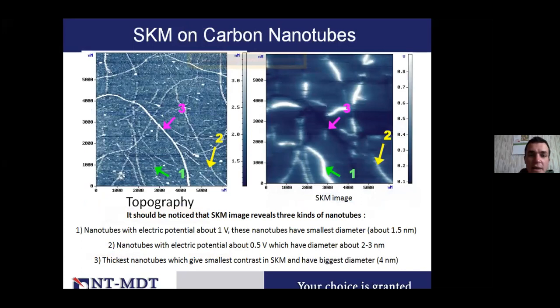So here you can see some example of the images of surface potential. So it's nanotubes distribution, and you can see on the left the topography, and on the right the surface potential of the same area. And you can see the different size nanotubes show different surface potential distribution on the right with quite high resolution. The scan size here is about 6 microns in XY.